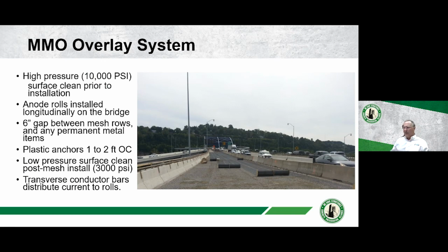Now, once you get all the wiring in place, you run the mesh on the surface, and they come in these rolls. Each roll is about 4 feet wide, 50 meters long. That's 162 feet. Those rolls are either touching each other, or they can be up to 6 inches apart. Typically, they're run right next to each other, and a transverse conductor bar connects them together. You apply your current, your copper wires are connected to your conductor bar, and that distributes the current through all the titanium mesh.